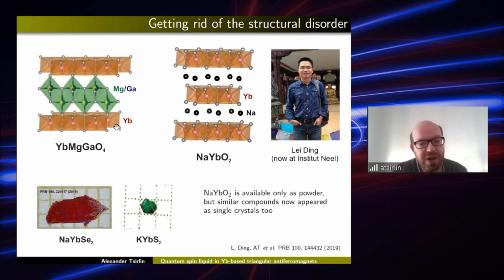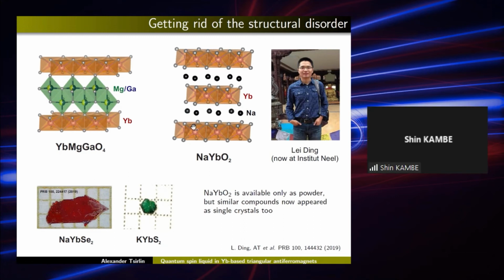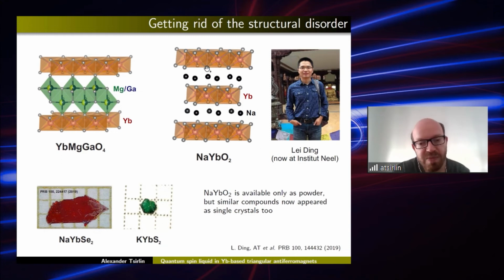So we know that the whole problem came from this interlayer space where we mixed magnesium and gallium. So we shouldn't mix them, we should replace them with something that has the uniform charge and shows no random distribution. One possibility is to put just the sodium atoms, and then we come to the compound NaYbO2, which actually has been known since a long time, but nobody ever paid attention to it because it is one out of 100 compounds with this rock salt type crystal structure, and at first glance they all look the same.